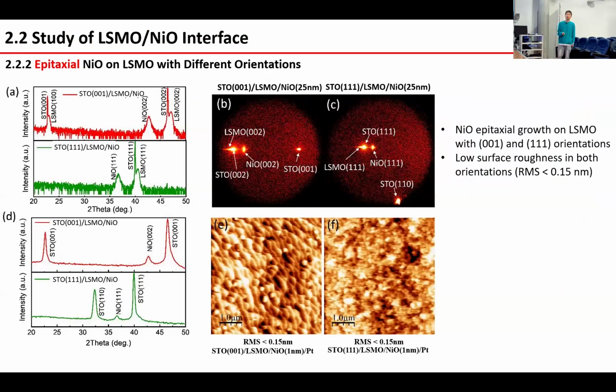And also we have studied the epitaxial growth of the nickel oxide on the LSMO with different orientations. We have grown on different orientations, like the 001 and the 111 orientation. The theta to theta curve shows a clear single peak, nickel oxide 002 and nickel oxide 111. And also the diffraction spot shows the single clear peak. And also the integration curve is relatively similar to the theta to theta curve, indicating single crystalline epitaxial growth on the LSMO.